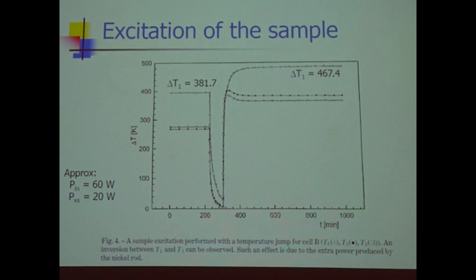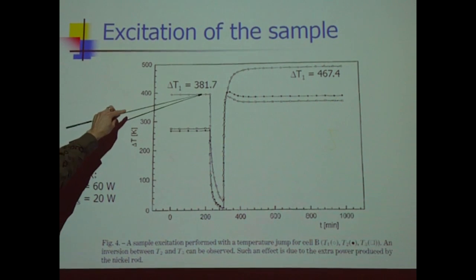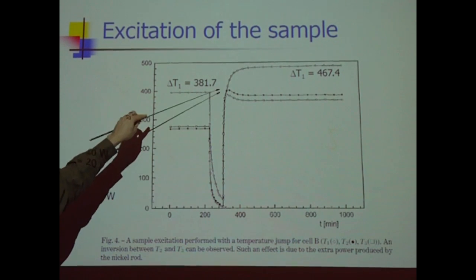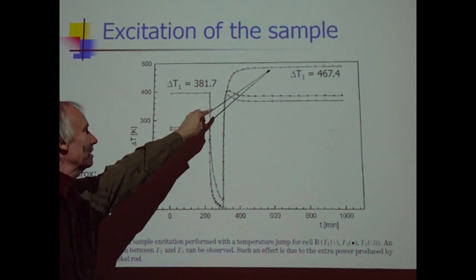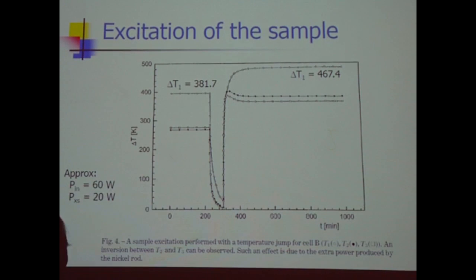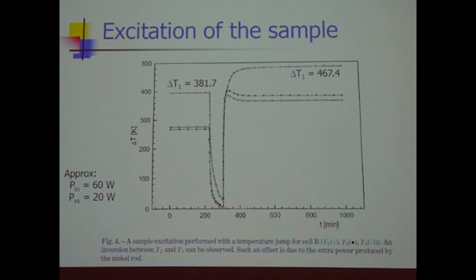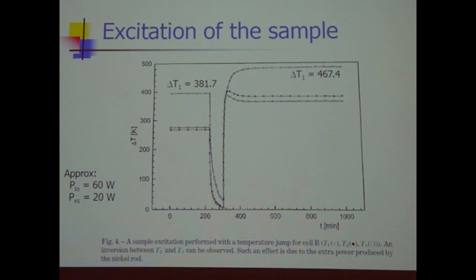So the basic observation, the basic claim, if you like, is that you're running the thing in power balance. You go, in this case, through a temperature cycle, and when you're done with the temperature cycle, the temperature's higher, which basically, between here and here, you're seeing that the temperature's higher because the nickel hydride is now producing excess power.